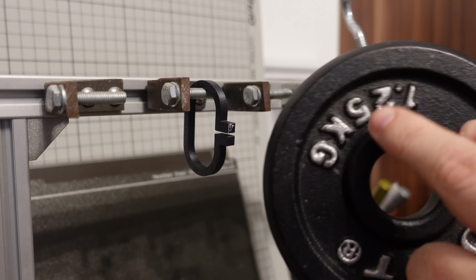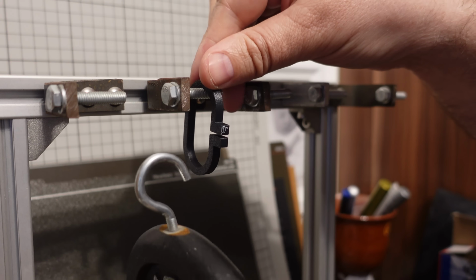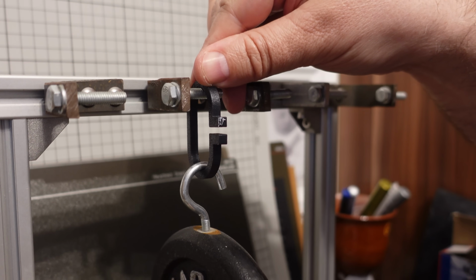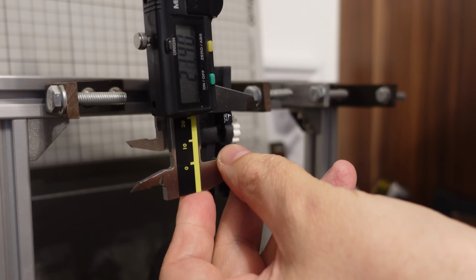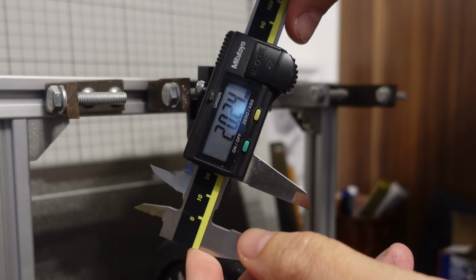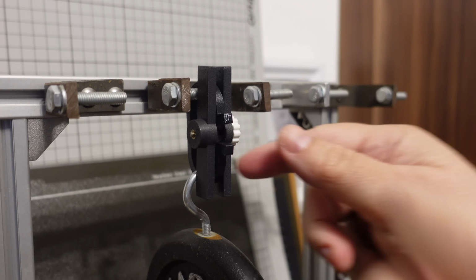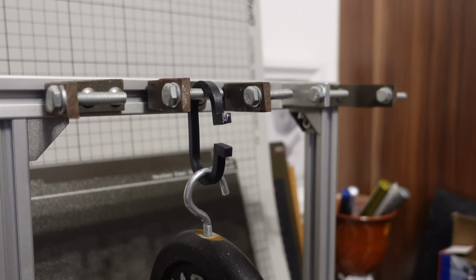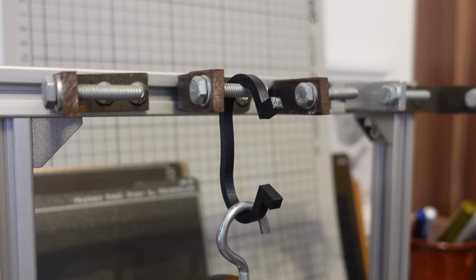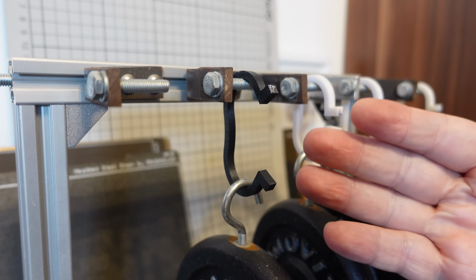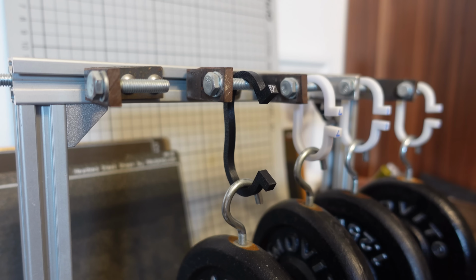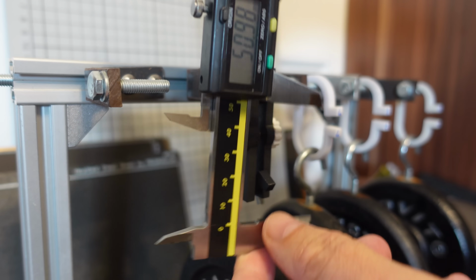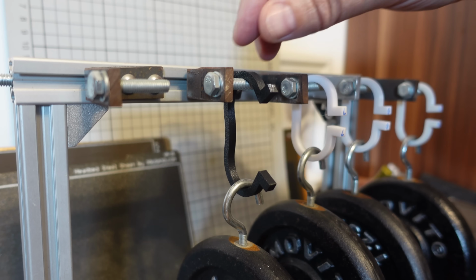The creep test measures deformation under constant load, but I'm not sure how it performs here. It's quite flexible. 20.24, the start deformation. I always measure them every day, but in a video I usually jump 5 days, but this is only after 1 day. I already measured it, but I'm showing this because I'm not even sure that it will survive 5 days. This is the last day. It slowed down with the creeping, but the deformation is huge. Let's measure it. 50.98. And let's remove the load.